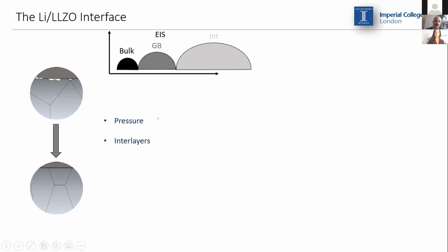Other groups have used pressure or interlayers in between the two cell components, and in that way they were able to decrease the interfacial contribution from the impedance spectrum. However, we are using another approach. As I mentioned in the first slide, we are thermally etching our samples. Initially, we were doing it to have nicer SEM images, so to reveal the grains.